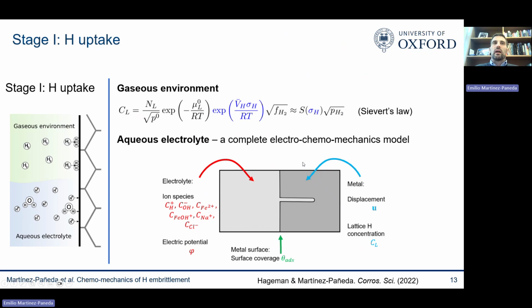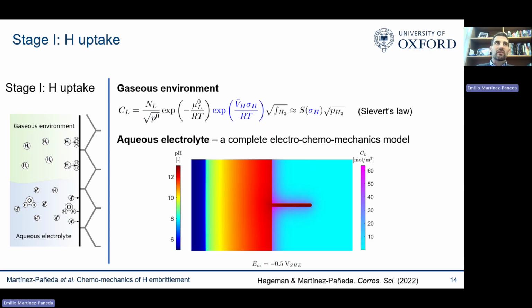The representative result that you get will be something like this, where I'm plotting on the electrolyte any relevant quantity, in this case the pH. You can see how it varies quite dramatically inside of the crack to the place where we do our measurements, hence why we need these modeling tools.